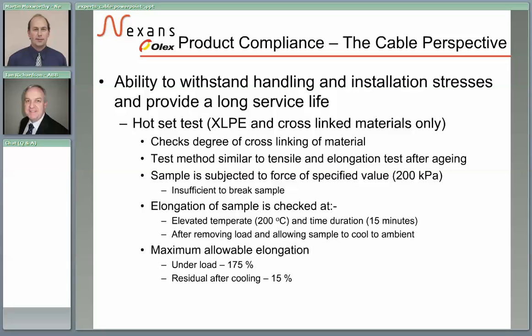Same sort of thing is done, but this time in the hot set test, the sample is subjected to a force of specified value, 200 kPa, and we measure the elongation after a set period of time at an elevated temperature such as 200 degrees. The pass criteria is that the test piece must not stretch more than 175% of its original length, and after cooling to ambient it must not have more than 15% residual elongation.